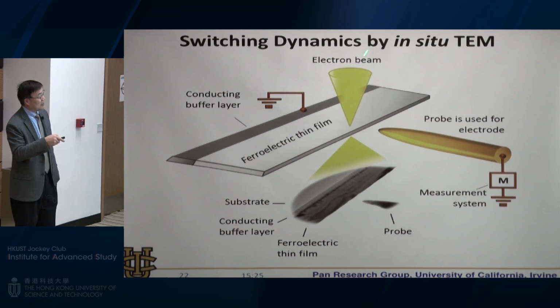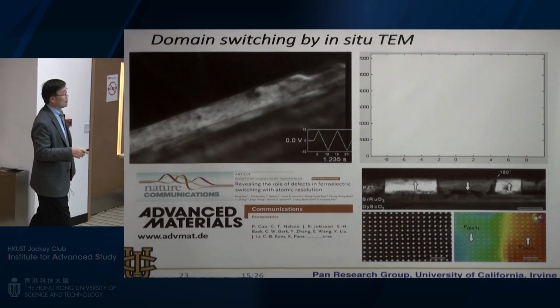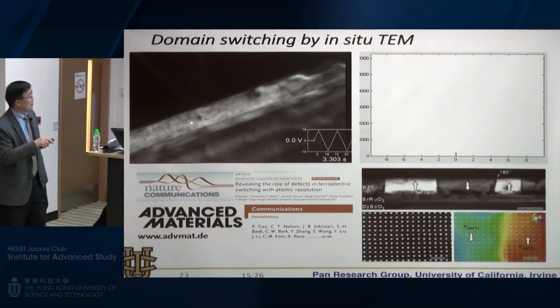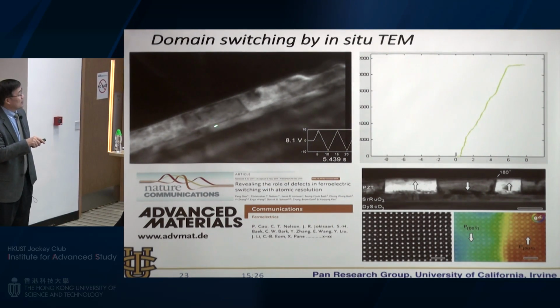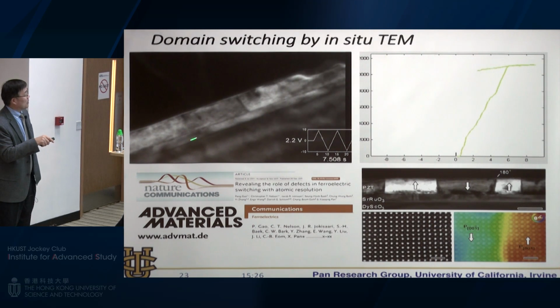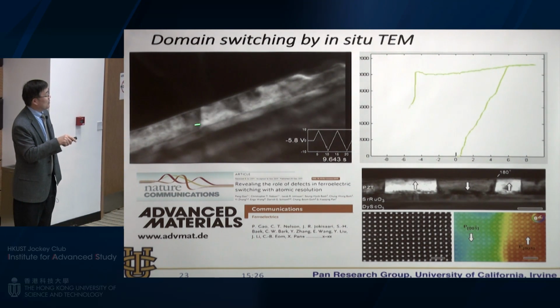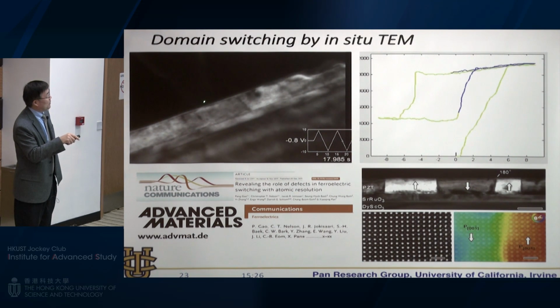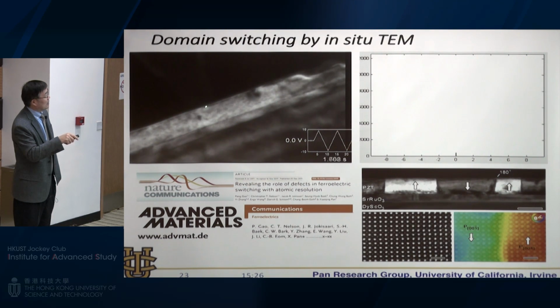And you can do electron microscopy imaging, and then apply an electric field and see how the structure and domain structure change. This is from real data. This is the substrate, this is the bottom electrode, and this is the PZT. And this is the STM tip, a conducting tip. The tip is pretty sharp, and we apply a field between the tip and the bottom electrode. This area can be switched.